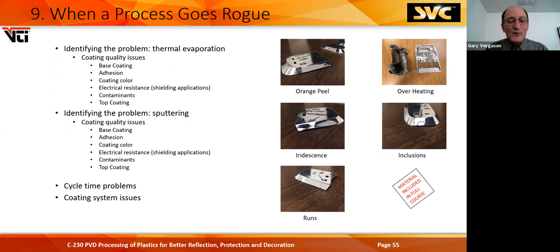This section with a full course is going to be fun. When a process goes rogue, and they will go rogue, you'll have all sorts of different issues, whether it's thermal evap or sputtering. Base coating can be bad. You can have adhesion, wrong color, your electrical resistance, you got contaminants. Top coating can screw something up. If you have an air leak in a system, you can have dark colors. If you got a water leak in the system, you can have rainbows. Your cycle time will drift all over the place. And you can have coating issues.